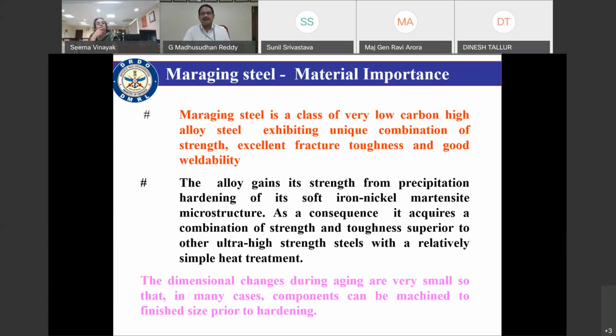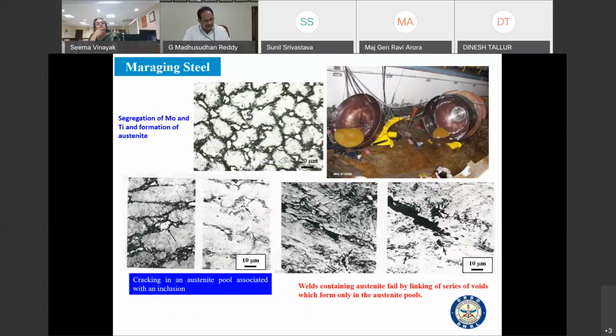The problem is here: whenever you are trying to weld it, there is a segregation of moly and titanium during welding, because this causes local enrichment. This causes local enrichment at the interfaces, and in the subsequent aging treatment, we are getting retained austenite. That is basically a subphase. During pressure testing, during actual loading, this is getting yielded, and we're getting a lot of voids. All voids are getting connected.